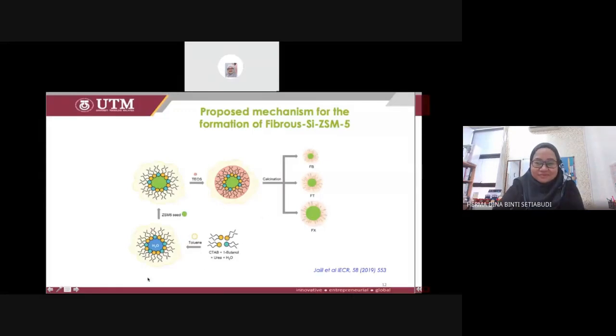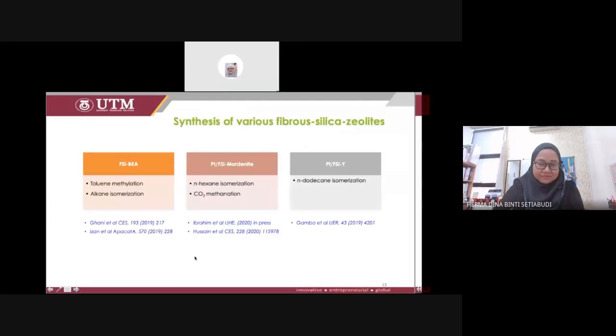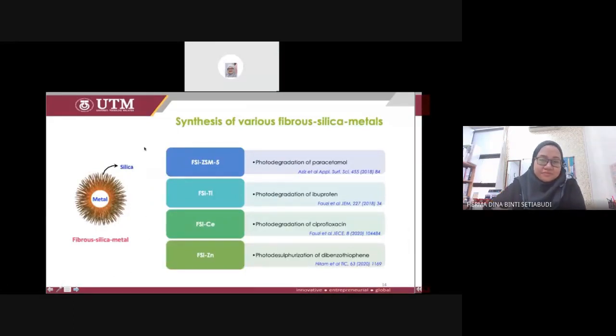Okay, this is some of the examples for the various fibrous silica zeolites. We also tried not only the ZSM5, but also zeolite beta, mordenite, and zeolite Y. And you can see here some of the successful applications on toluene methylation, alkane isomerization, hexane isomerization, CO2 methanation, and also dodecane isomerization. Other than gas reactions, we also tried the fibrous silica material, like fibrous silica ZSM5, on a liquid phase reaction, which is photodegradation of paracetamol.